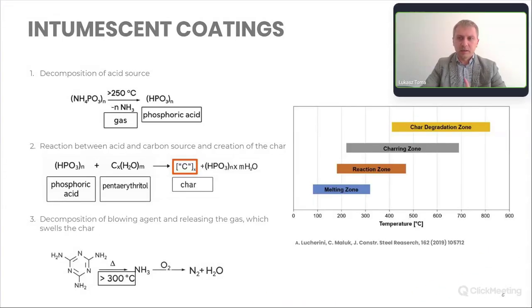What is important is the expansion factor, the ratio between the height of the char and the initial coating thickness. It can be even up to 100. So for example, if we have at the beginning a layer with a thickness of 1 millimeter, as a result of this creation of char, we can have a layer of char of even 10 centimeters. So it's kind of impressive, really.